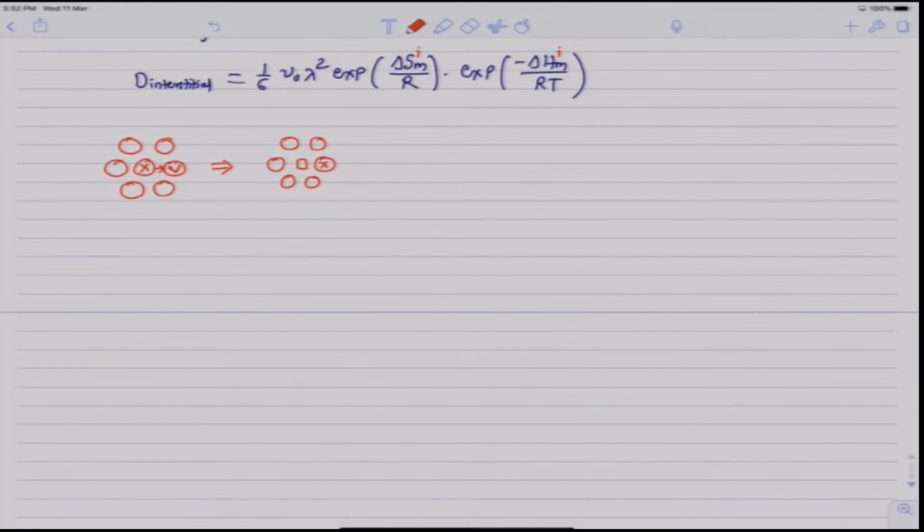Why is it not unity? Because vacancy itself is making random jumps, and for vacancy there is no barrier for vacancy formation as for the diffusion of X. The only barrier for diffusion is the migration barrier, and so the number of successful jumps of a vacancy per unit time will be much higher than that for the atom X. So, the vacancy itself will make n number of jumps and after making n number of jumps, it can come back to one of the nearest neighbor sites of x, and then this x will make its second jump into that same vacancy.